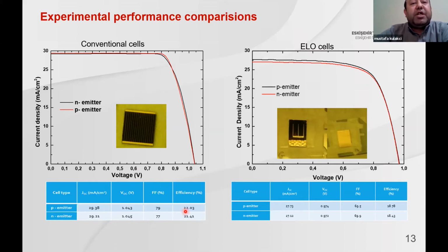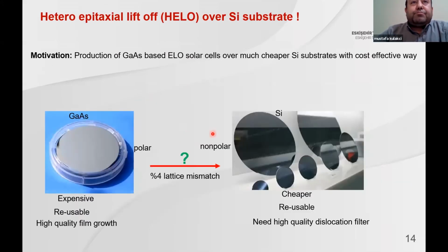Then in the projected case, it can reach about 27%, maybe, if you make a better contact shape. Of course, these contacts here are very thin. Actually, it needs much more electroplating over it, but we have no infrastructure to do that. The same things also hold for ELO cells. Okay. 5 minutes. Okay, I am going to finish rapidly.